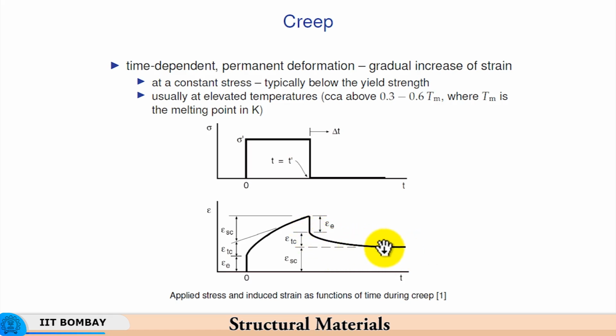following which this slowly settles to a permanent strain or permanent deformation, and that is where it becomes a little objectionable, because even if you have not reached the yield strength, still because of holding the material for a long time at a high temperature under a certain working stress, you have some permanent deformation in the material. So, this creep is a very different phenomenon compared to our usual phenomena of yielding and plastic deformation. Here a permanent deformation takes place because of creep.